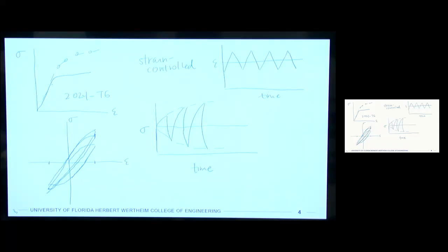And then we could continue this process. And you can see that the hysteresis loops are getting sort of tighter and tighter the longer we go. So the effect diminishes. We can't get increasing strain hardening forever because we'll eventually get to high enough stresses and strains that the thing will eventually fail. But you can see these are called hysteresis loops.